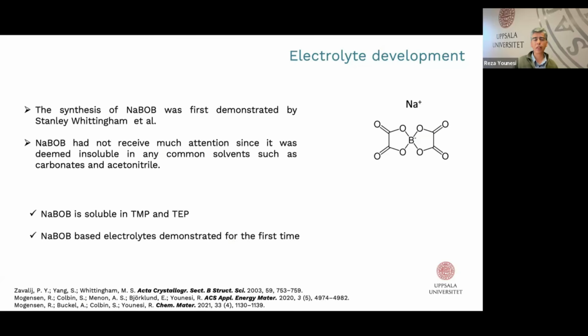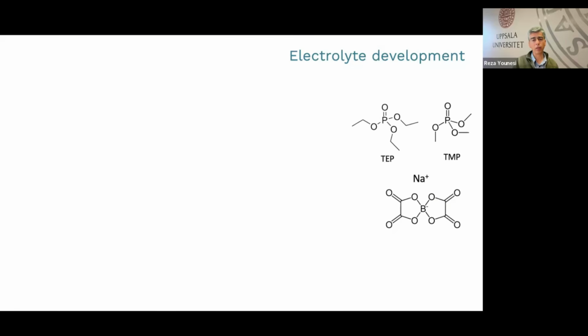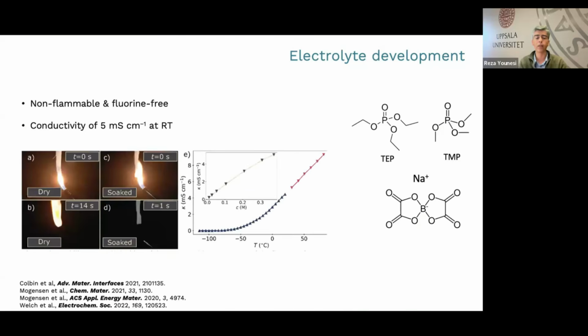But then we found that we can dissolve sodium BOB in alkyl phosphate solvents like TMP and TEP. We tried to understand how this electrolyte works in terms of SEI formation, stability, and aging in sodium-ion batteries. By using this electrolyte, we could form a non-flammable, fluorine-free electrolyte providing a conductivity of roughly 5 millisiemens per centimeter, which is not very high - definitely lower than a standard carbonate-based electrolyte - but it's still quite good and acceptable ionic conductivity, especially for low C-rate batteries like C/3 or C/2, which can easily be handled.